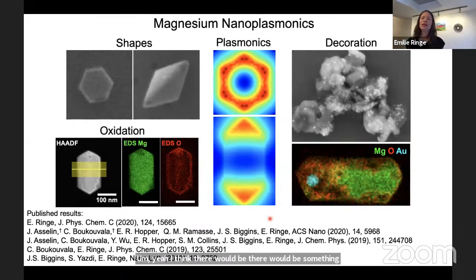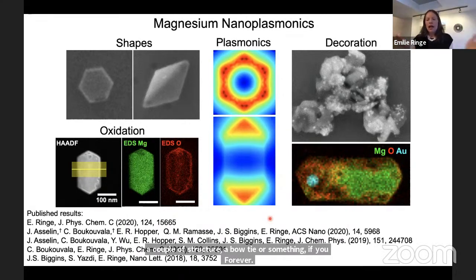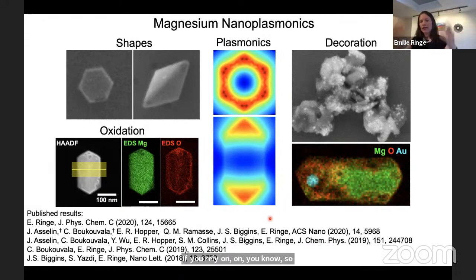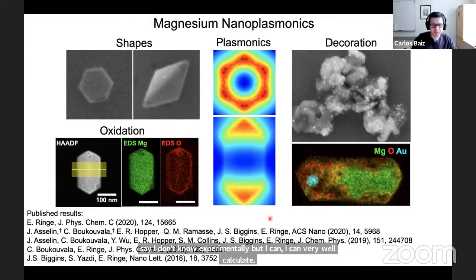Again, this is a little bit tricky to make because these are not fabricated structures. If you want to make a coupled structure, a bow tie or something, if you fabricate, well, that's relatively simple. If you rely on a solution of stuff and you deposit that on the grid and then you see how the particles land, well, then it's a little bit heterogeneous. It's great for studying the stuff, but in terms of an application, it's a little bit less reproducible. But yeah, hotspots would be created. Again, someone can ask what would be the effect of the oxide layer, which I could say I don't know experimentally, but I can very well calculate. Indeed. Yeah. Thank you.